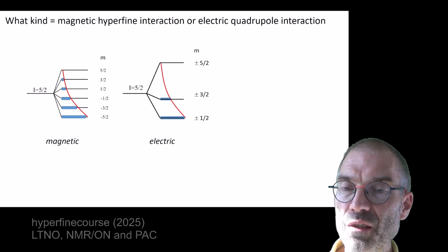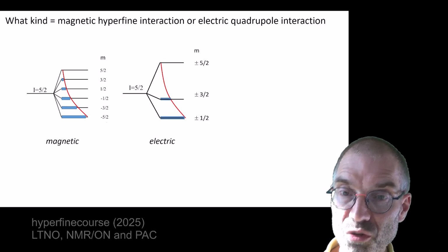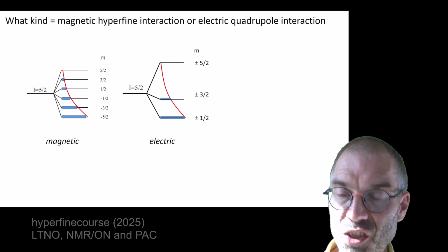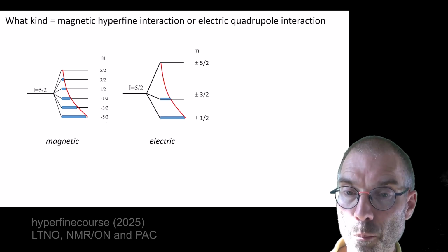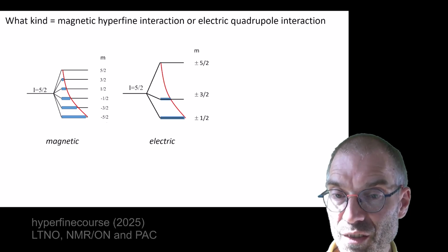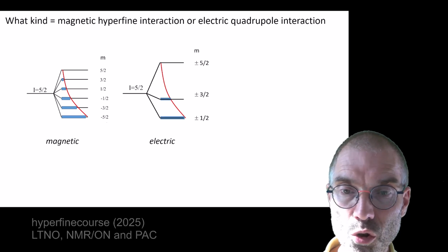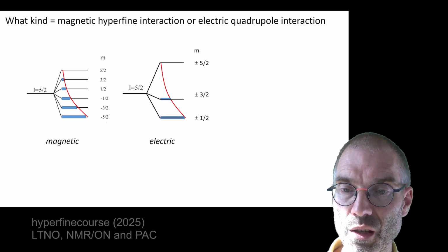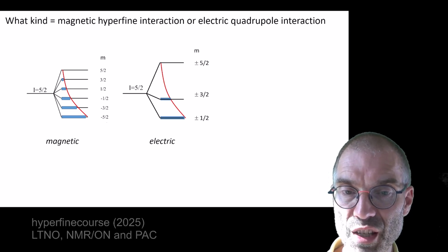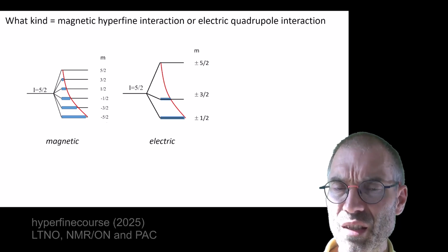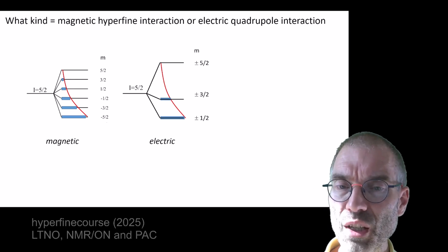So that would mean, if the spins are predominantly pointing along the negative z direction, the negative z-axis, then there would be most photons emitted along that z-axis, so an increase in counts along the z direction, which is not what we observed. There was a decrease in counts along the z direction. So this makes it unlikely that the magnetic hyperfine interaction is the correct answer.